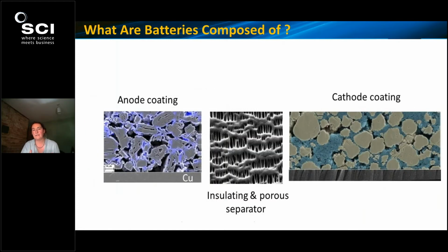But when we look inside the layers, on the left you can see a cross-section of an anode coating, which is composed of graphite particles with conductive additives and a polymer binder to make sure that all the components are coherent, but also adherent to a current collector, and are porous enough to allow an organic solvent to infiltrate all of the coating to enable lithium ions to diffuse efficiently and uniformly.